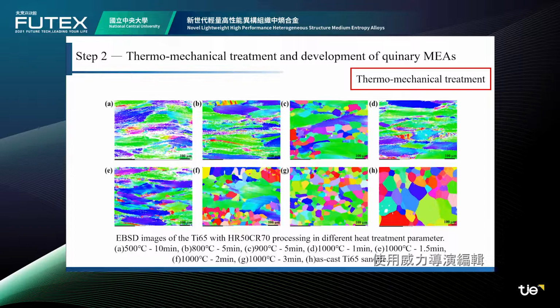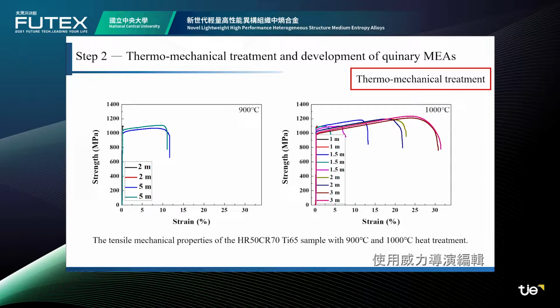On the other hand, when annealing at a high temperature for a short time, the recrystallized grains can effectively nucleate and refine, which are about 70% smaller than the casting alloy. In mechanical properties, it can be noticed that the grain size here has little effect on the strength of titanium 65 medium entropy alloys. Besides, the time of the heat treatment plays an important role in plastic deformation.